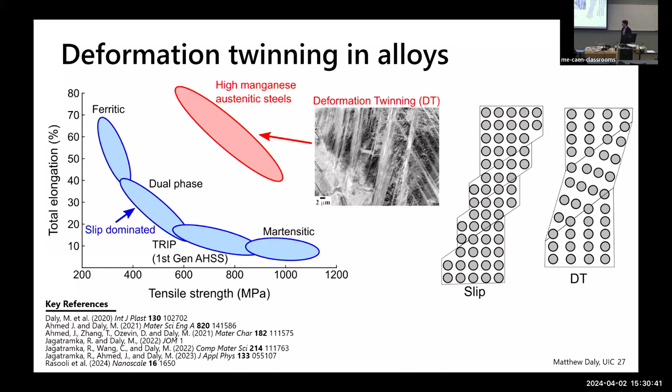And what we're going to be ultimately looking at is the competition between two deformation mechanisms, slip and deformation twinning. Just as a review, I'm sure many people are familiar with slip and twinning, but if you'll indulge me, there are a lot of ways you could describe slip, and I've got this simple cartoon schematic here, but basically the way I like to think about it is a non-correlated operation of dislocations. So the dislocations glide across slip planes, and when they leave the crystal, they move in a way that accommodates the far field deformation you're applying on the system, and they may interact on different slip planes, but when they finally leave, the crystal structure is undamaged, but there is macro flow of the material.